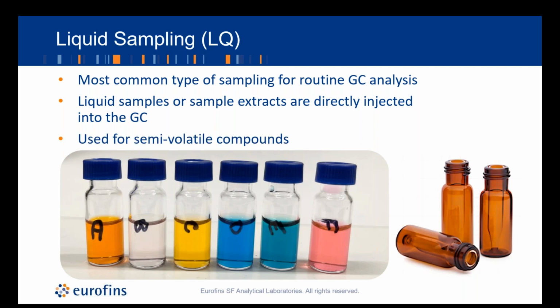And this can be useful for semi-volatile compounds that are difficult to get into headspace gas. However, you have to consider that with liquid samples, you typically have to dilute them before you can inject them. And for solid samples, you would need to do an extraction first, which can result in selectivity of what you see depending upon the extracting solvent or technique you use.